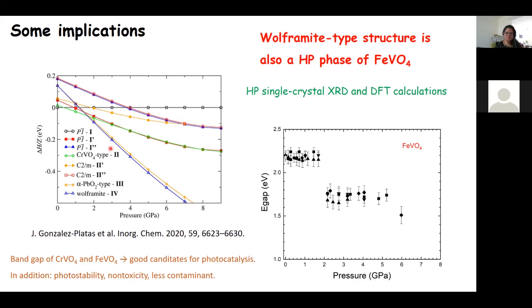So most of these compounds crystallize in the same structure. All of them have a common systematic going to these low symmetry monoclinic structures. And you can see here on the band gap that you have again band gap collapses with the transition. In this one, it has already a band gap of 2.2 eV at low pressure. And so the band gap becomes much smaller than in the other compounds under high pressure.